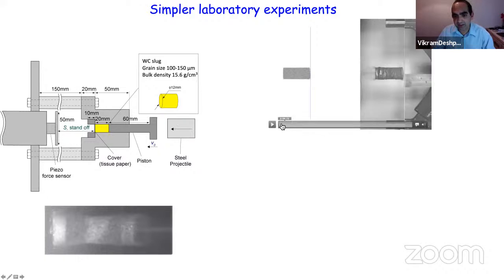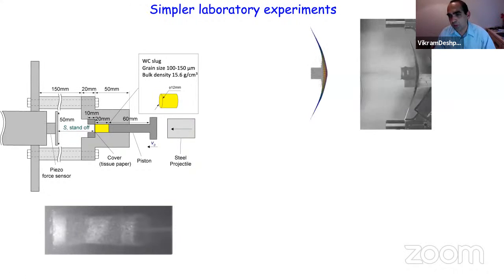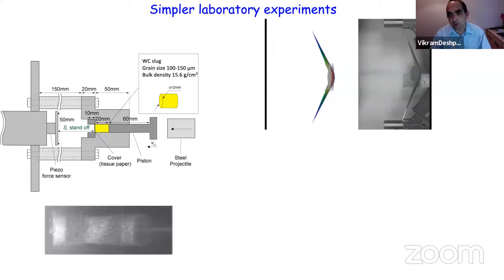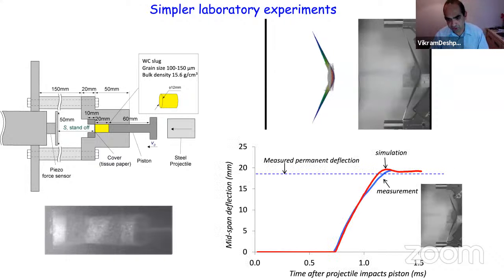And when we do that, this on the right is the experiment and the left is the simulation, it all works out remarkably well. So now you can see that we're getting extremely good agreement between the experiments and the simulations, including if I just plot the mid-span deflection as a function of time, it all looks rather good. So this tells us that we've got a good simulation capability, we've got a good handle over the experiments, and now we can really use these experiments to probe what we want in terms of design of structures that will help.